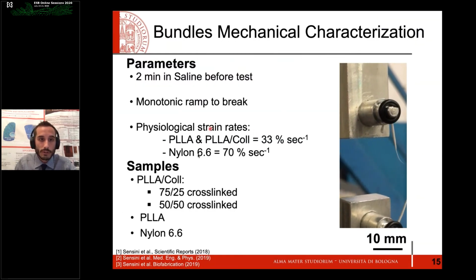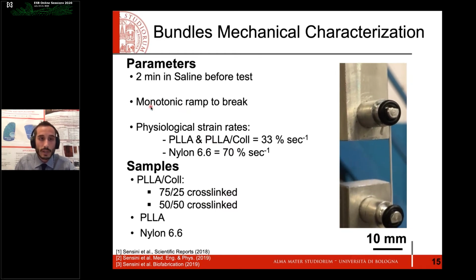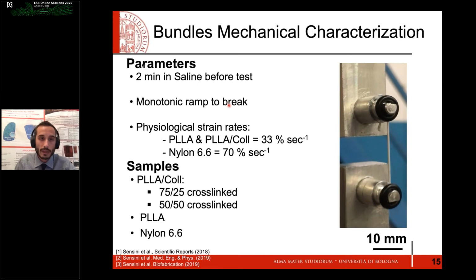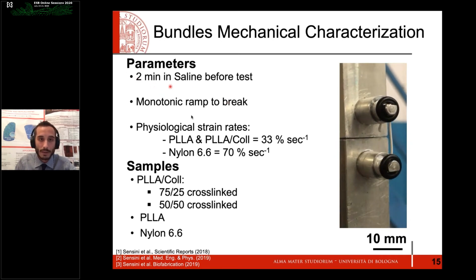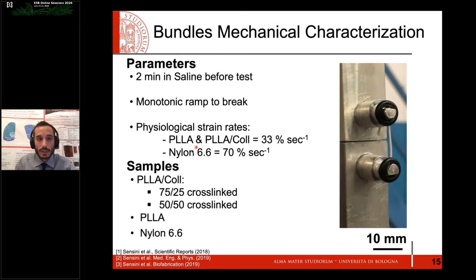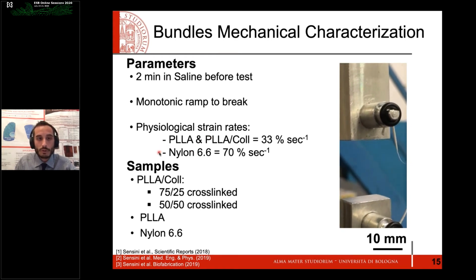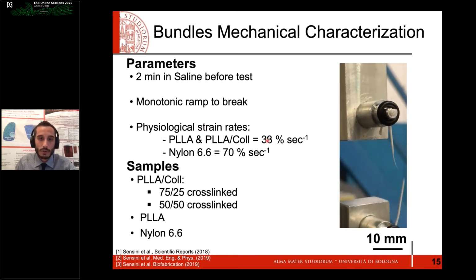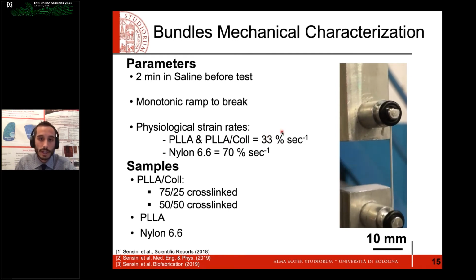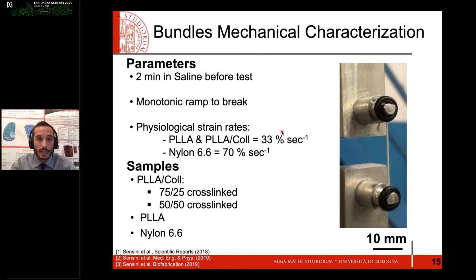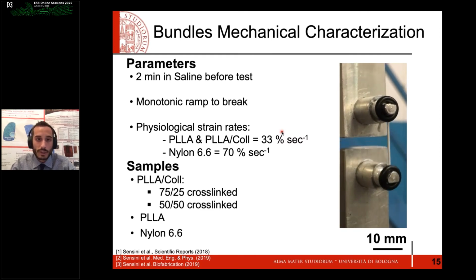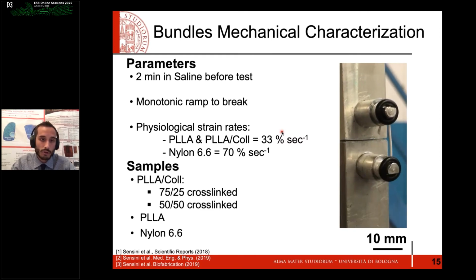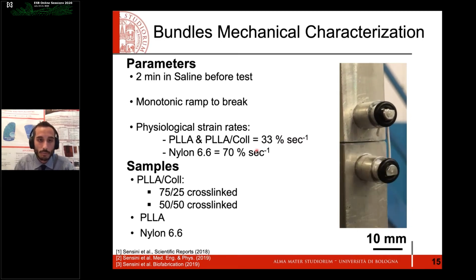We also tested in several studies the mechanical properties of our bundles using a tensile test, consisting of a monotonic ramp to break, immersing the bundles in saline before the test. In these works, we used different physiological strain rates. For the regenerative bundles, we used a 33% per second strain rate, according to the limited kinematic task that a patient can perform after surgery during the rehabilitation period.